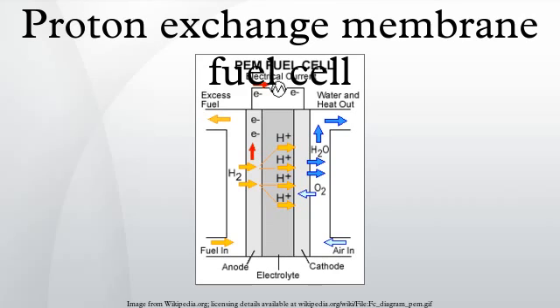Recently, a Canadian research institute has dramatically increased the performance of this type of iron-based catalyst. Their material produces 99 amps per cubic centimeter at 0.8 volts, a key measurement of catalytic activity. That is 35 times better than the best non-precious metal catalysts so far, and close to the Department of Energy's goal for fuel cell catalysts, 130 amps per cubic centimeter. It also matches the performance of typical platinum catalysts.